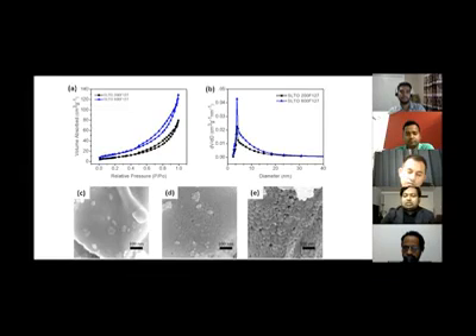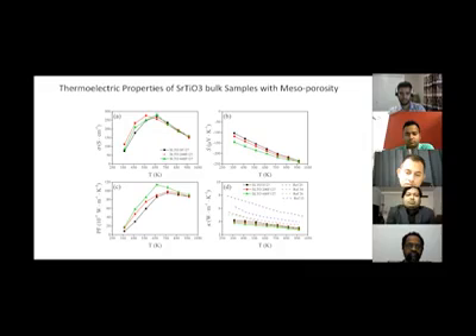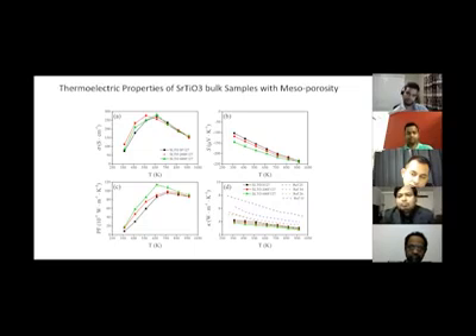And we did the thermoelectric property measurement. The first graph in the rightmost corner is the electrical conductivity. We can see initially it's showing semiconducting behavior with the temperature, but it becomes metallic later. If you see the graph, it is increasing initially, so it's semiconducting behavior, and then it's going down, which is metallic. So we get reasonable electrical conductivity for our material, and with the porosity we have improved the Seebeck coefficient.